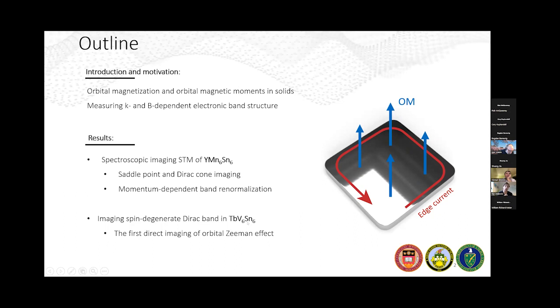And then in the second part of the talk, I will tell you some of our very recent work on terbium vanadium tin, 166. One of the advantages of this system is that it has a simpler magnetic structure. At low temperature, it is a soft ferromagnet, so it has very low coercive fields. It also has a very low Curie temperature that's, very coincidentally, around the liquid helium temperature. So it's, again, favorable for STM to study in and out of this ferromagnetic state.